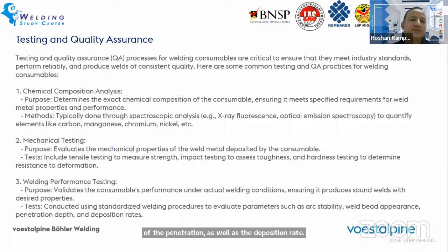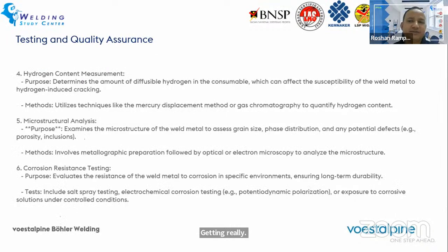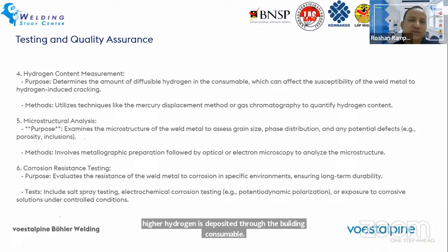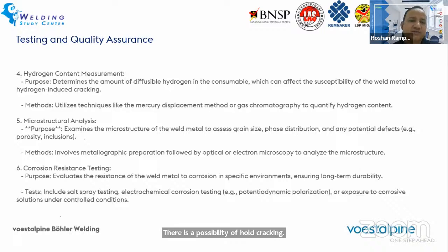Then measurement of the diffusible hydrogen content. Why is it important? Because for most steel material, we do not want higher hydrogen content in the weld deposit, because if higher hydrogen is deposited through the welding consumable, there is a possibility of cold cracking or hydrogen induced cracking in the weld joint or HAZ, and also in the base material.